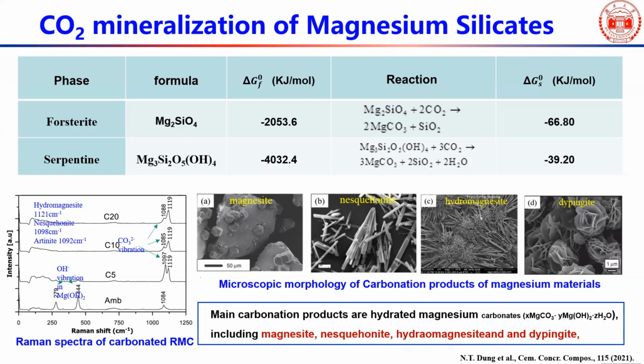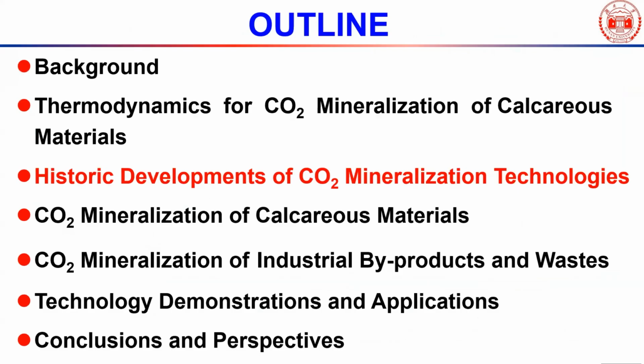So there are some processes that can convert magnesium silicates to magnesium oxide, so they can then be carbonated very quickly. Also, you can see that for magnesium silicate and magnesium silicate hydrate, the energies for carbonation are also very negative, but on the other hand, they cannot be easily carbonated at room temperature.